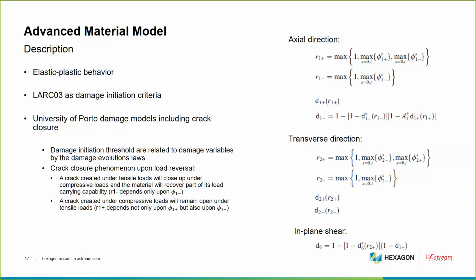And we have the possibility to take into account the crack closure when we reverse the loading. So typically, if a crack is created under tensile loads, it will close up under compressive load, and the material will recover part of its load carrying capability. So that's why we see here that we have the propagation law R1 minus, which depends only on the compressive condition. But on the opposite, a crack created under compressive load will remain open under tensile load. So that's why here we have R1 plus, which depends not only upon the failure in tension, but also on whether we have seen some compressive load prior to the tension condition.